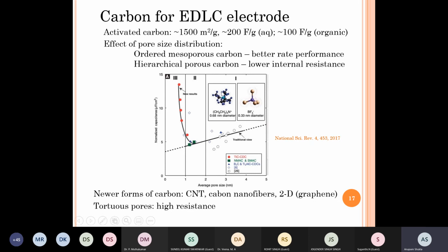However, the ion has a certain diameter, and when the pore size becomes less than the hydrated ion diameter, the ion will not be able to enter the pore. If that happens, the smaller pores will not contribute to capacitance, and therefore the capacitance will go down. So as the average pore size goes down, the capacitance will go down, and there were studies which actually showed that. However, then there came newer studies showing that if you go much below that range, capacitance actually starts to increase, and people have researched why this happens.